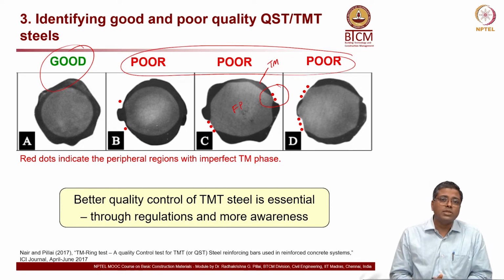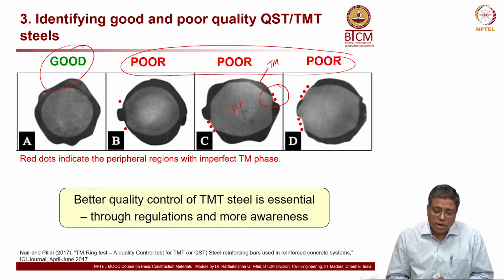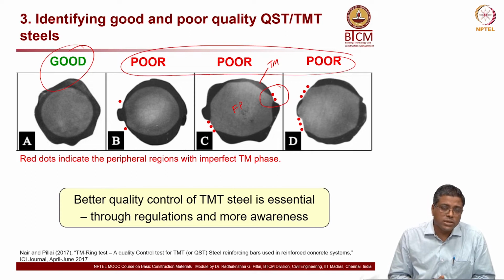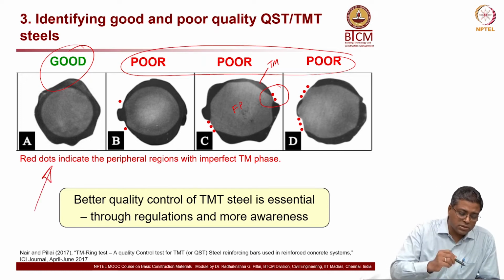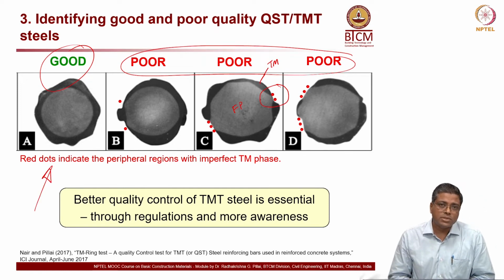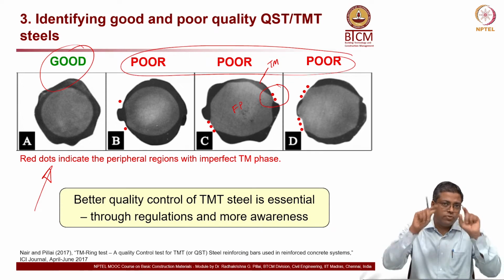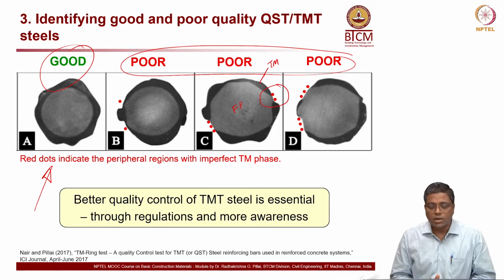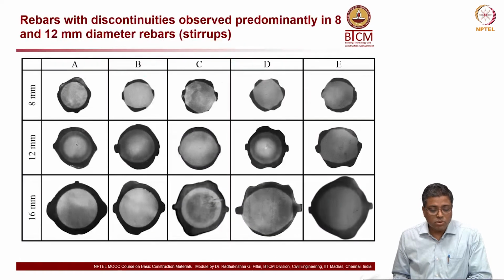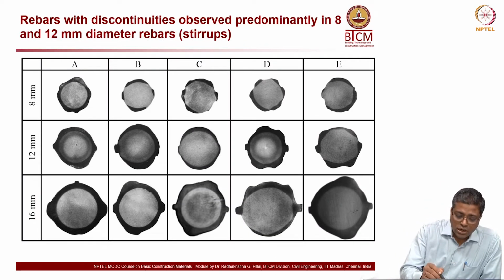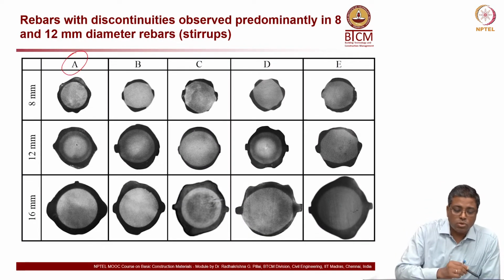Why this is happening is because the steel manufacturers sometimes don't quench the steel properly. If uniform quenching is happening, then you will get a bar like this. The one on the left side is a good quality bar with a full ring, very good quality, also in terms of corrosion resistance. Now you see here, only type A is good in this.